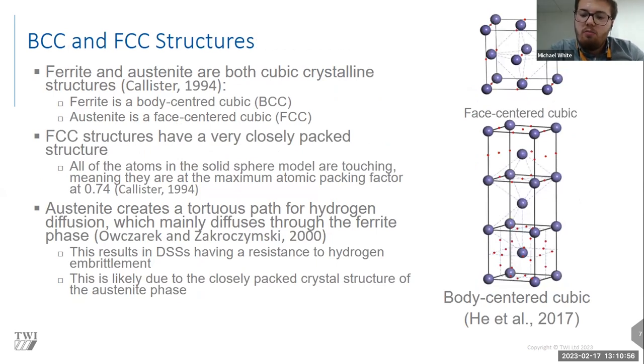So as I just mentioned, both FCC, or face-centered cubic, and BCC, body-centered cubic, structures were tested during the experiments. FCC structures make up austenite and BCC structures make up ferrite. FCC structures are shown to have a significantly more closely packed atomic structure than body-centered cubics, represented by their atomic packing factor of 0.74, which is the highest possible atomic packing factor that can be achieved for a crystal structure. Atomic packing factor represents the percentage of a unit cell which is occupied by the hard spheres shown in the image on the right.